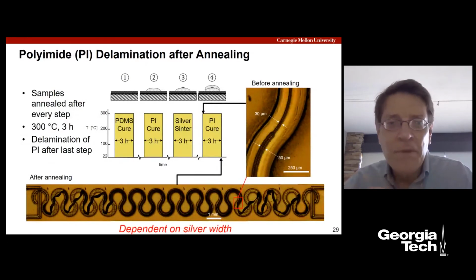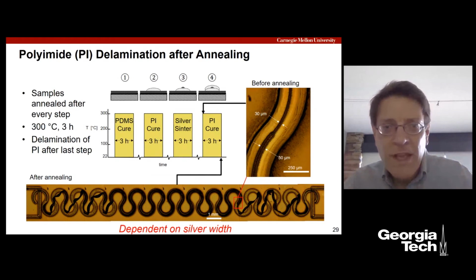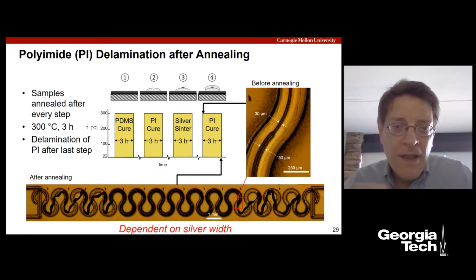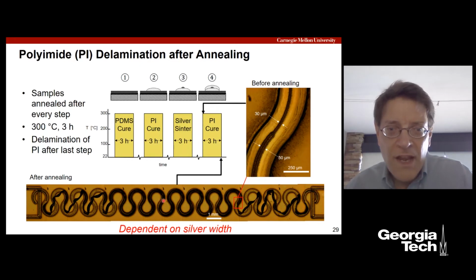So that was problem number one, the PDMS. The second problem we encountered was really interesting: the issue of delamination of the polyimide. We'd made these meander patterns. Here you see a meander pattern of interconnect where you see delamination clearly in certain regions and not others.